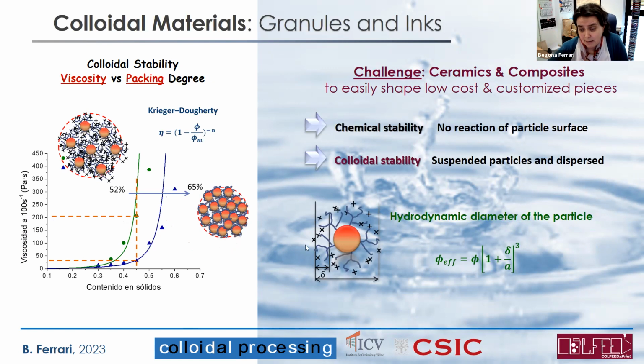So this hydrodynamic diameter is going to influence packing. In fact, we can measure the viscosity as a function of the solid content in our suspension, and we can speculate, depending on the hydrodynamic diameter, how the rheology evolves. And with a packing model like the Krieger-Dougherty, we can measure the maximum packing density that we can achieve with this suspension. So for example, if you have a huge hydrodynamic diameter, we are going to achieve a lower green density in our 3D piece, compared to using another kind of stereochemistry of the polymer that is adsorbing on the particle.